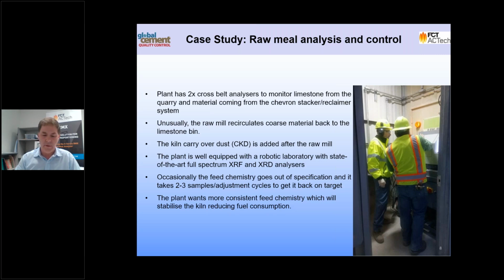In addition to all of this, they've got some other difficulties managing the feed materials. One of them is the coarse material that comes from the raw mill. So that's the largest stone that sometimes gets knocked out the side, and that gets sent back into the limestone feed bin, which alters its composition. They also have a kiln dust recycle that is added in after the raw mill, which means that's not accounted for either. And so what they do is they use estimates for these things, but it's not always possible to get the composition exactly right for all of these streams that are going into the process.